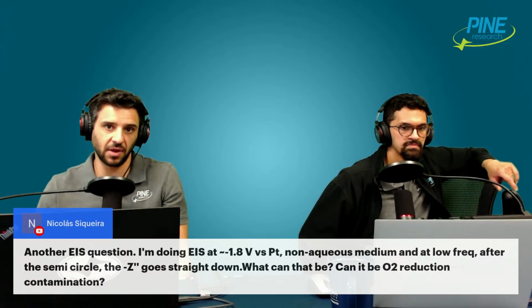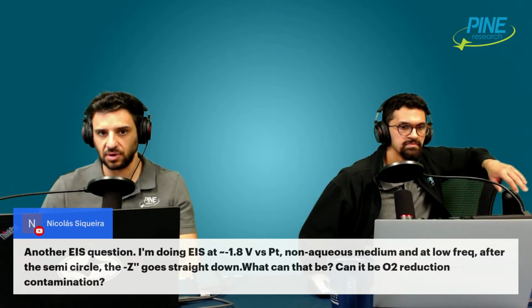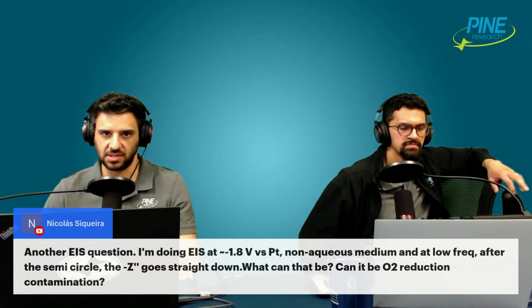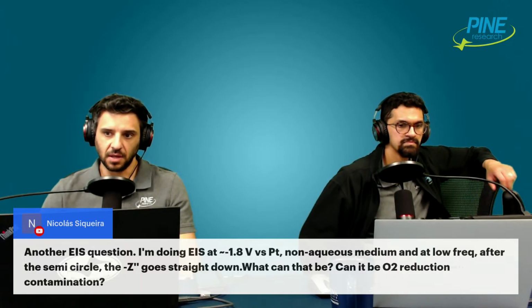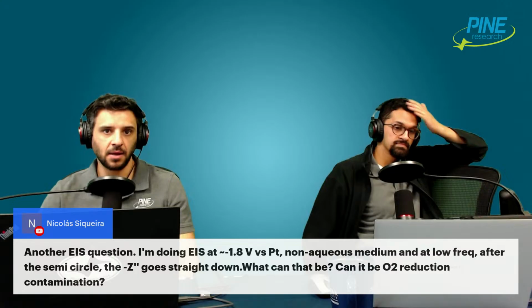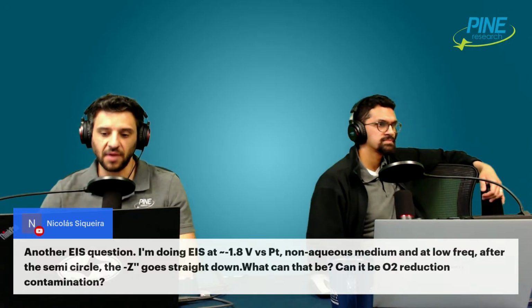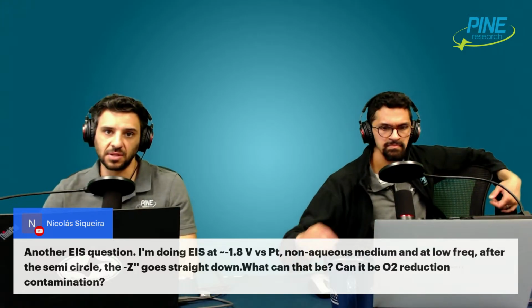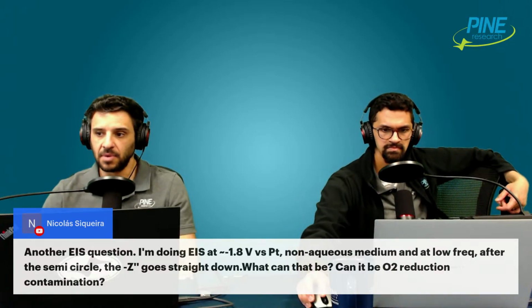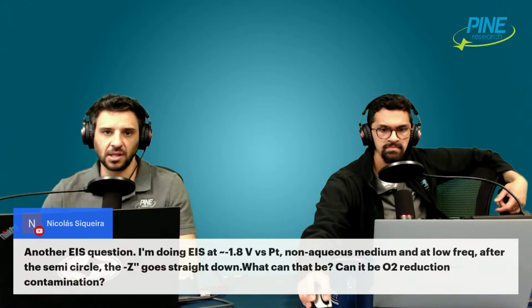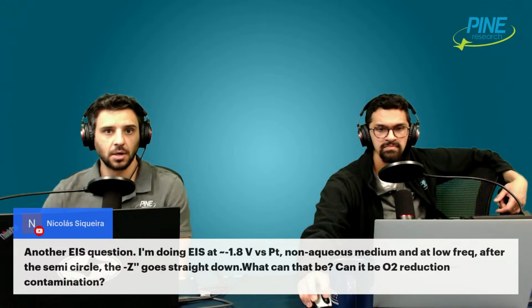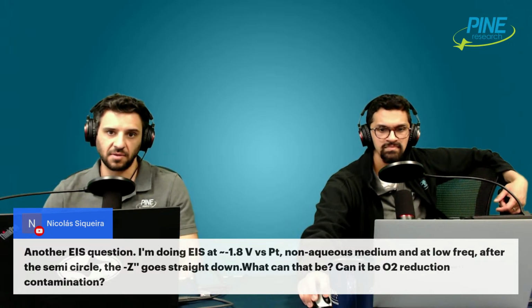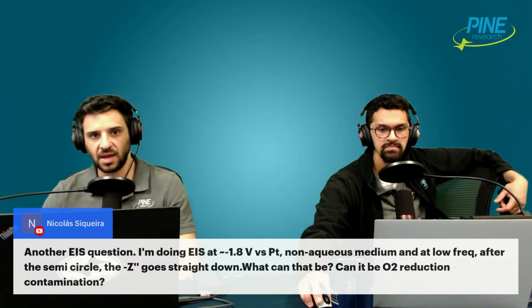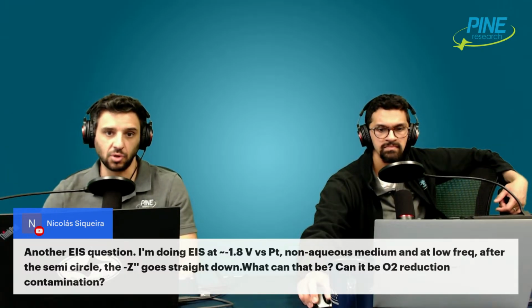So for a couple of reasons. One of them is it's low frequency. So very possibly things are drifting, there's mass transport stuff going on, and the potential is drifting real bad because platinum as a reference is a pseudo reference and isn't really fixed anywhere. Your impedance data, especially at low frequencies that take longer, could be all out of whack. And so the fact that it's going straight down means nothing. It could be going straight up, straight left, straight right. It could be nothing.